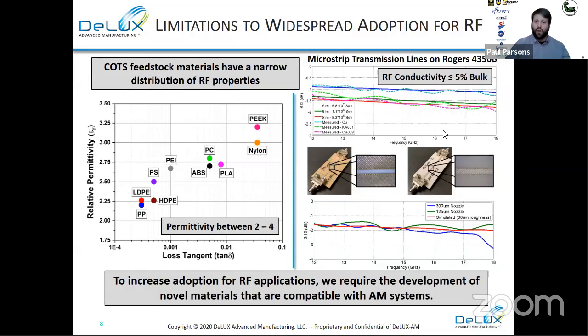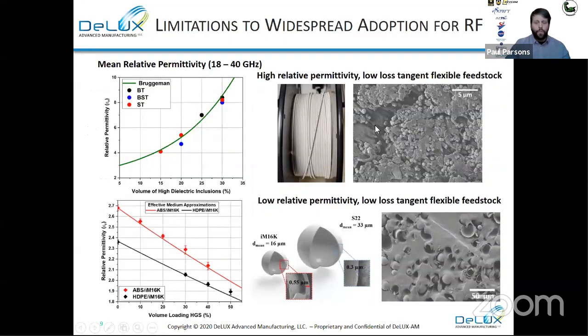So in order to increase the adoption of AM towards RF applications, we require the development of novel materials that are compatible with AM systems. We've done that with the first example by producing our own flexible, low dielectric loss tangent feedstock filaments. Looking at the mean permittivity of these materials, we've developed both high dielectric materials and low dielectric materials. These sorts of composite filaments are created by introducing very specific inclusions that control volume fractions. Provided that these inclusions are very small compared to the incident wavelength, the effective properties of the composite are essentially a mixture of the properties of the polymer and the inclusions themselves.